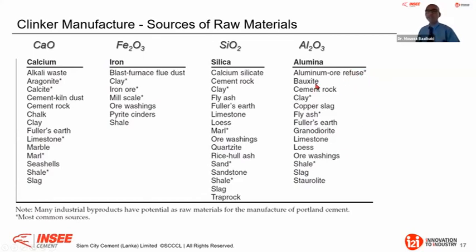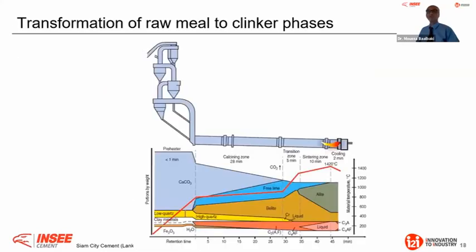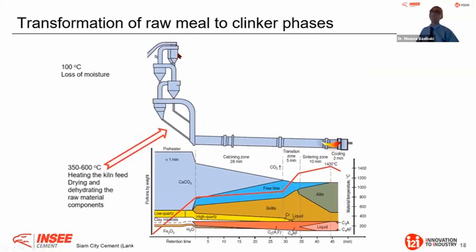Therefore, with all these materials, the raw materials, we produce raw meal. And the raw meal goes to the kiln. In the kiln, we have two important parts: the preheater and the core of the kiln. In the preheater, we put the raw meal in, and we start to heat, dry and dehydrate it. If you look at the temperature profile, we can go up to 600 degrees, and mainly you see that the calcium carbonate, the limestone, is the main constituent of the raw materials.